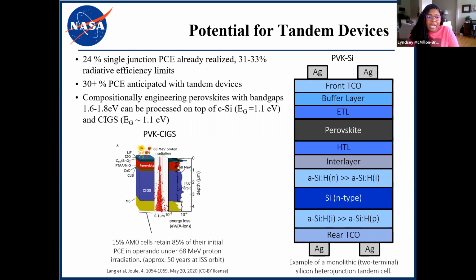So I'd like to switch gears a bit and do some forecasting for the field. And I really think that there's great potential for perovskite tandem devices. Single junction power conversion efficiencies for perovskites have already reached about 24%, and they have radiative efficiency limits in the low 30% range. So the combination of exceptional photovoltaic properties and tunable band gaps in a wide range and low temperature processability really make perovskite materials attractive for multi-junction tandem cells. And it's anticipated that we could easily achieve about 30% power conversion efficiency with tandem devices. And they have radiative efficiency limits of around 42%.